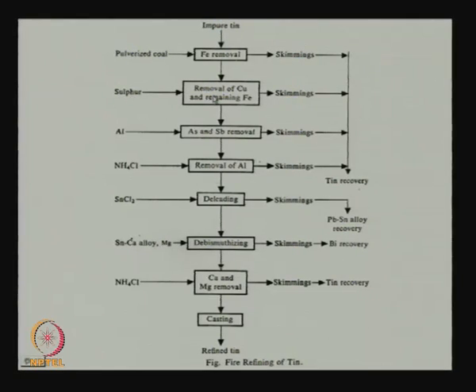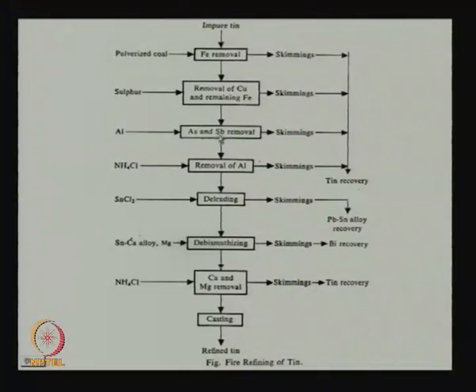We will add sulfur, that will remove copper and remaining iron. These will all be skimmings, these will all be solids that will come out and be removed. We will add aluminum, skimmings should have arsenic and antimony. Ammonium chloride for removal of excess aluminum, skimmings. All these skimmings will go again for tin recovery, because they will all have some entrapped tin.